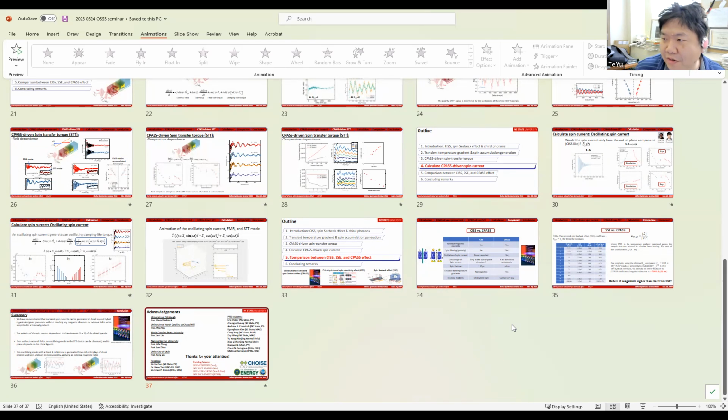Nice talk. I have a question about how critical the sample quality is to see those things that you saw? Well, it's perovskite. We don't need a very high quality sample, but it's just a spin-coated hybrid perovskite sample. Of course, we needed to control the morphologies very well to make a flat interface, and also the thickness of the hybrid perovskite. But most of the technical challenges are how to incorporate the cation in the perovskite and to achieve a very high CD signal. So the chirality synthesis is the difficult part. For the processing, it should be straightforward.